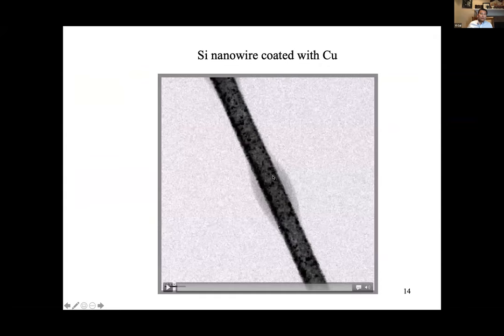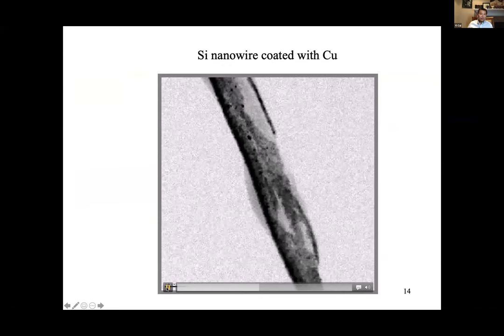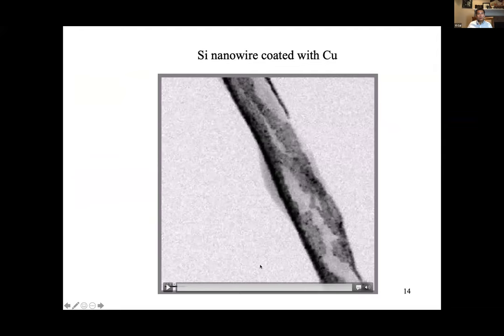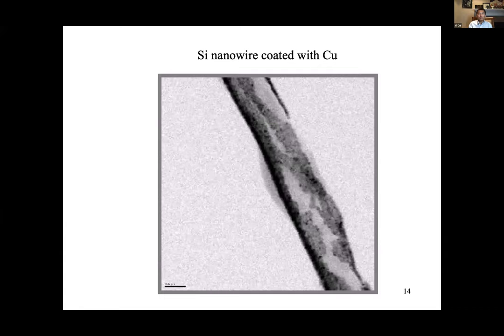The first video I want to show you demonstrates how dramatic this change is. This is a 200-nanometer scale bar, so roughly 200-nanometer-diameter wires. When you put lithium in, you can see the volume expansion is gigantic. This nanowire surface is coated by copper; you're driving electrons in and lithium diffuses and the electrochemical reaction takes place. This volume expansion has a huge thermodynamic driving force, and is so powerful that the surrounding copper coating is broken. However, these nanowires — they survive. They don't break.